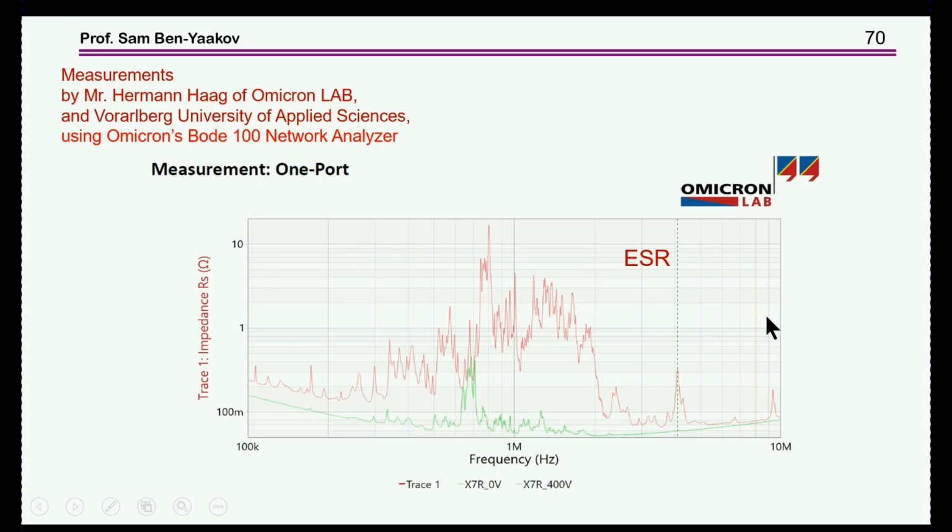Now we found that when you look at the ESR of a capacitor with a network analyzer or with a tester, and when you expose it to DC, you get even higher piezoelectric resonances. So now we have another phenomenon, that the DC is affecting the piezoelectricity of the device. Again, don't ask me why, I really don't know. I'm just reporting the fact. That is a problem.